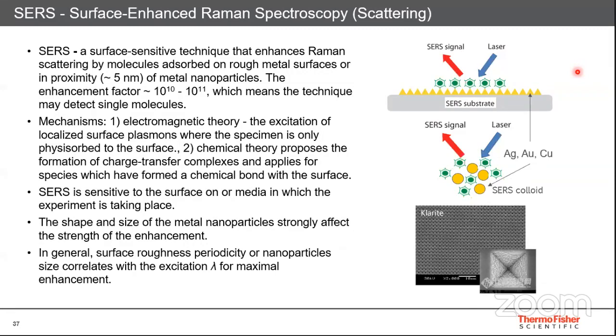What they do is have the adsorption of the molecule on metal surfaces or metal nanoparticles, because of which their interaction results in an enhancement of the Raman signal by about 10 to the power 10 or 10 to the power 11 times. Even if there is just one molecule, it can give you a strong signal in Raman. Because when you're looking at food technology, you're looking at very small components, like foreign particles or pesticides. They are in a very small amount, but you want to detect them because they are very detrimental to human life, even in small concentration.